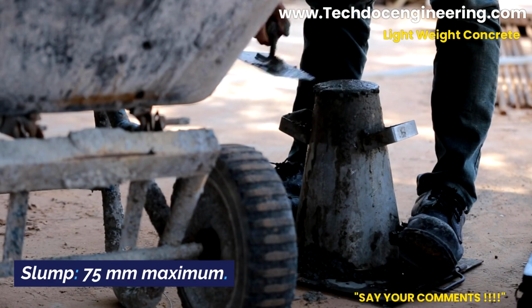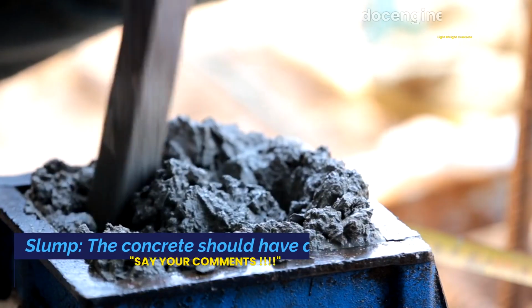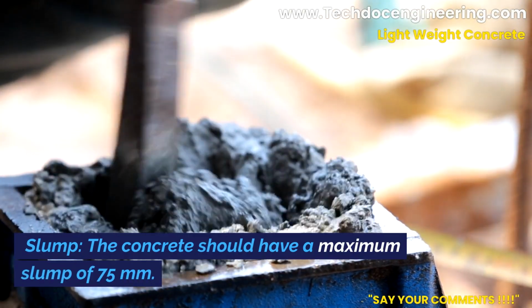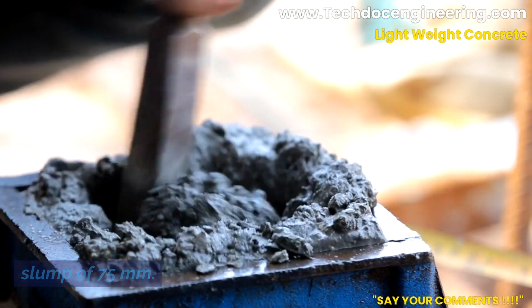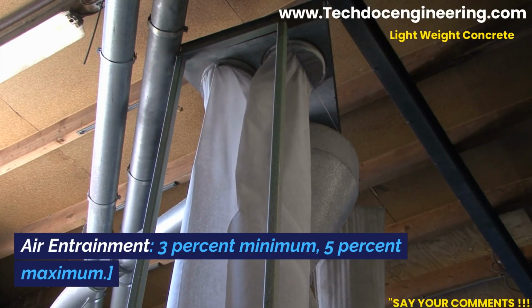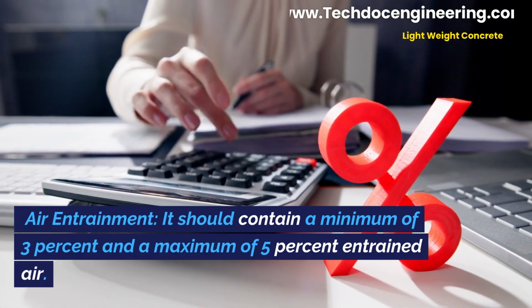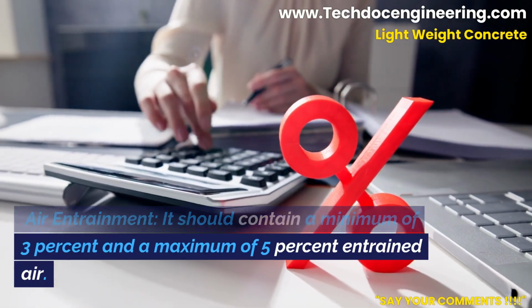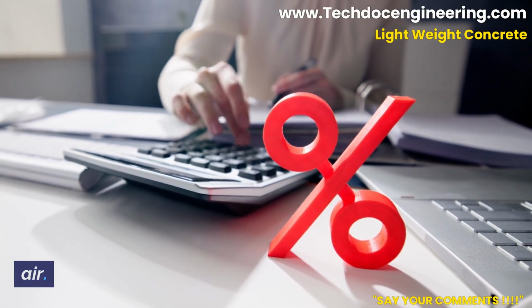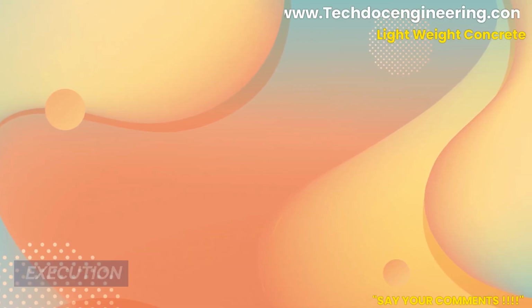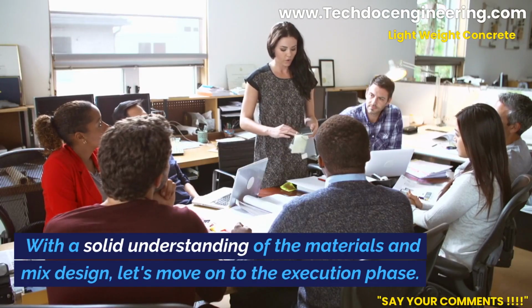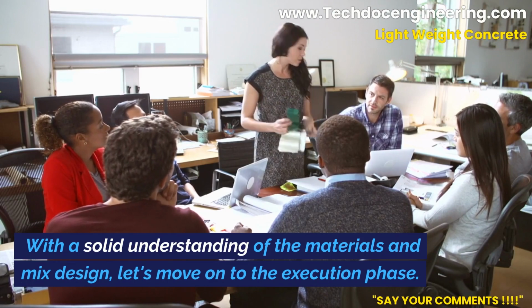Slump, 75 mm maximum. The concrete should have a maximum slump of 75 mm. Air entrainment, 3% minimum, 5% maximum. It should contain a minimum of 3% and a maximum of 5% entrained air. Execution. With a solid understanding of the materials and mix design, let's move on to the execution phase.